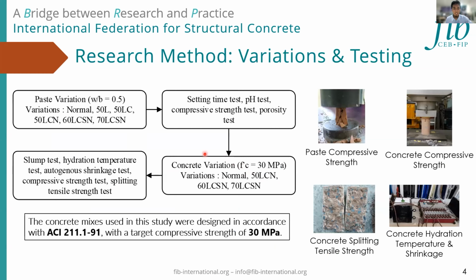This research is separated into two sections, the paste variation and the concrete variation. There are 6 variations of paste specimen: Normal as a control specimen, and starting from 50 to 70% of cement replacement. So the first 2 digits in here show the percentage of LC3 that replaces cement. The letter L denotes LC3, the letter C denotes additional 5% calcium carbonate. The letter N denotes that some of the water has been replaced with natrium hydroxide solution. And the letter S denotes an additional 5% GGBFS.